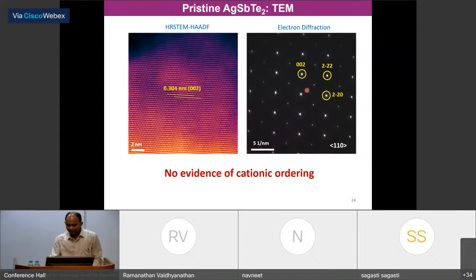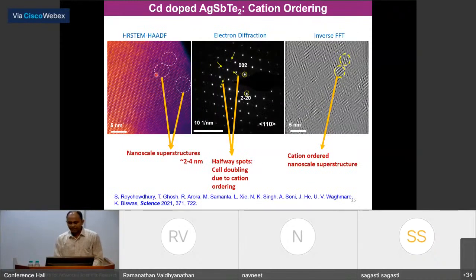Let's see, when we dope cadmium, we see the intensity distribution. So this is the nanostructure domain which is formed by cation ordering. This is the 6% cadmium doped sample, and if this is visible clearly, in the electron diffraction you can see very, very weak halfway spots. So that is basically the cell doubling. So cadmium is doubling the cell in different directions and creating this ordering of the structure, which is seen by HR-STEM high-angle imaging. And this creates nanostructure domains, which are 2 to 4 nanometers in size.